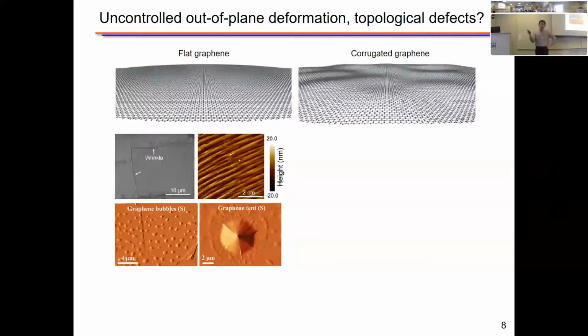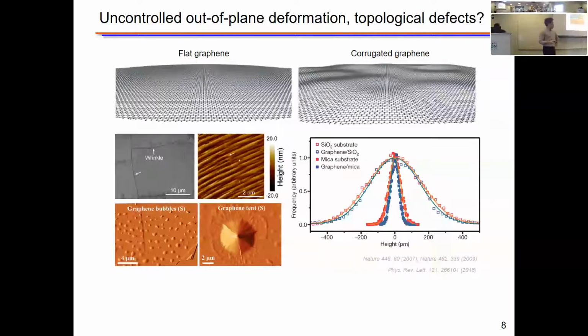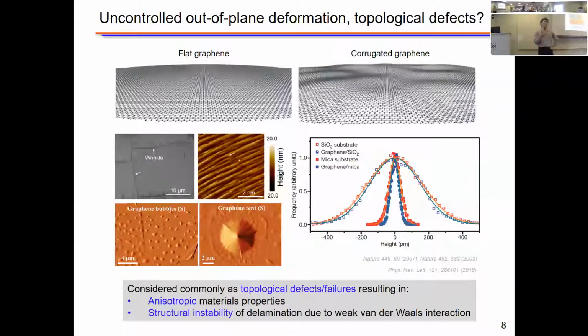So from the synthesis to transfer processes, in order to minimize total energy in response to the external stimuli, 2D material tends to form out-of-plane deformation in the form of wrinkles, buckle delamination, or bubbles. So people have been trying to make what they call ultra-flat graphene by depositing on various substrates. But still, this type of uncontrolled out-of-plane deformation has been considered a topological defect that gives anisotropic material characteristics, or even failure that deteriorates the mechanical integrity of 2D material-based systems. So people have been working on controlling this type of out-of-plane deformation to enhance functionality.